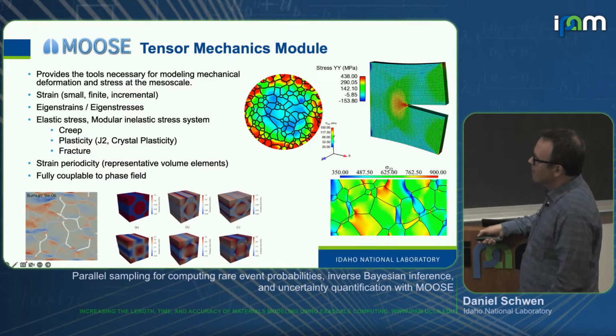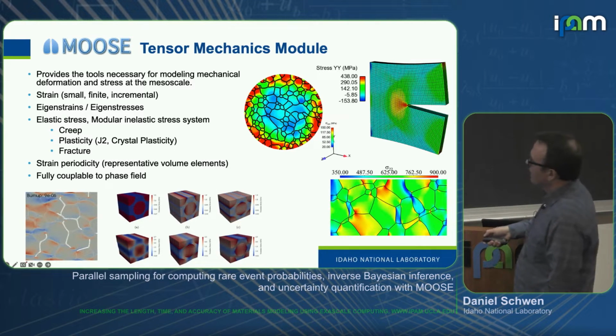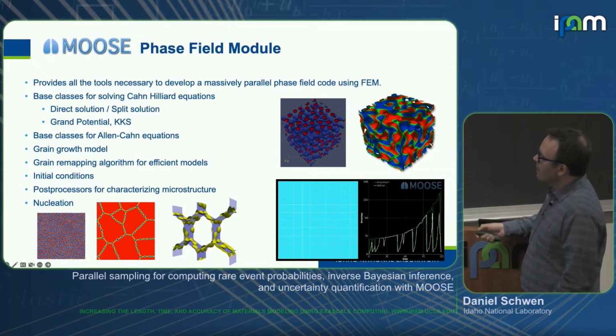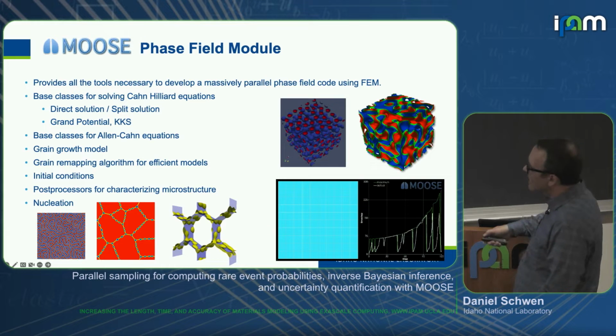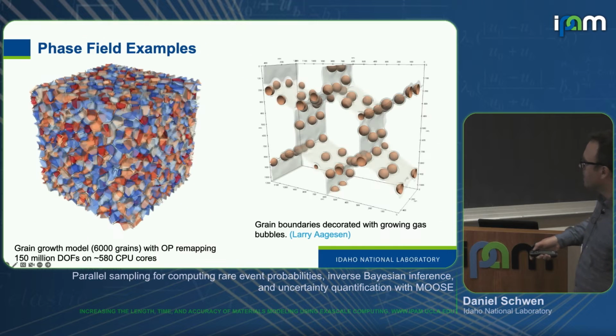We have things like strain periodicity, so you can model representative volume elements. Here you have grain boundary fracture, and here you have grain growth driven by elastic energy or strain energy. And then there's the phase field module. I already heard from a couple of people they don't like phase field modeling. They're very skeptic because it doesn't handle fluctuations and nucleation, for example. Anyway, I have a slide on that. So that provides the tools to develop parallel phase field codes using finite elements. I have all the base classes for solving Cahn-Hilliard and Allen-Cahn equations, multi-phase models, KKS potential, grain growth models, and we have a system for nucleation.